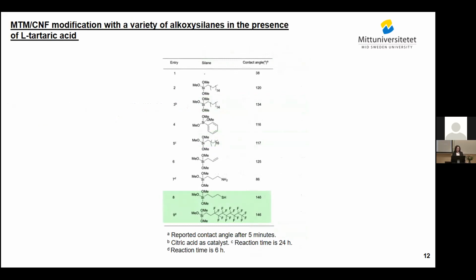I continued the modification with the L-tartaric acid, and here I noticed that the modification with the fluoroalkane is faster. In 6 hours, it reached a high contact angle value, but the result of the mercaptosilane is comparable with the fluoroalkane. We know that fluoroalkane is toxic; it is not environmentally friendly, but when we used the aminosilane, we couldn't reach a hydrophobic surface. But I should explain here that I couldn't improve the reaction beyond 6 hours.